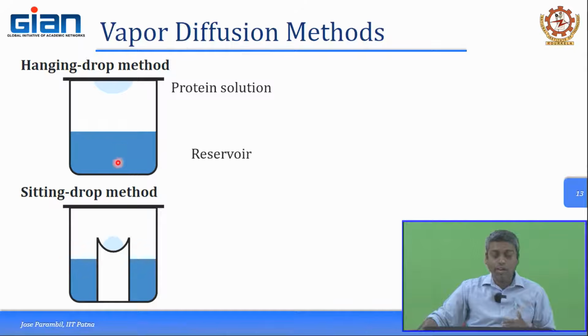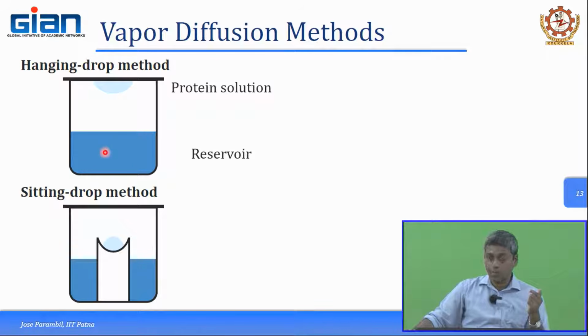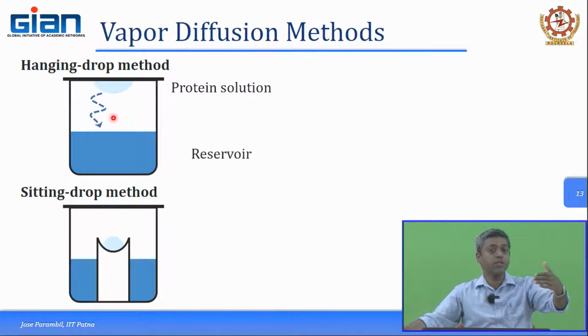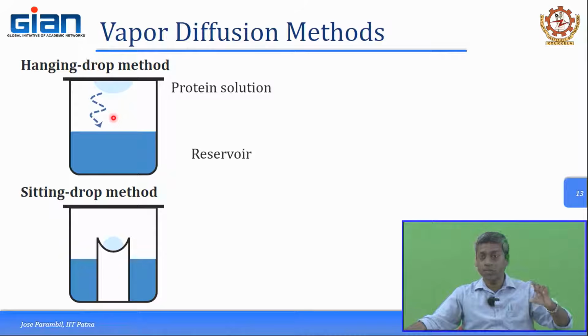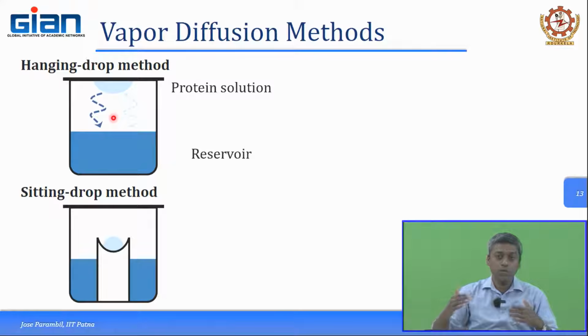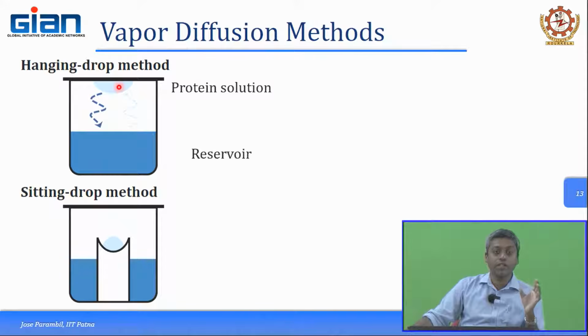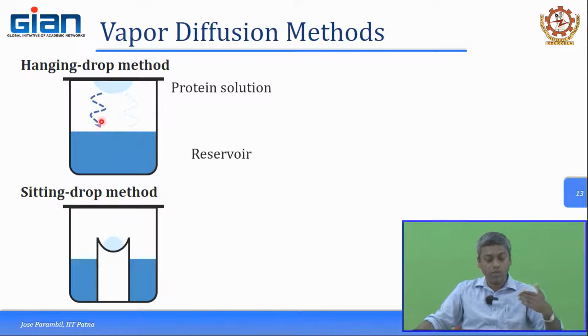Now, if you have got a higher solubility in a higher concentration of salt or buffer or maybe other polymers in the reservoir, typically the solvent used in both is the same, typically water. Water would start evaporating and moving. There would be a net movement of water from the protein solution on the top to the bottom reservoir. Simultaneously, there would also be a movement of water from the reservoir to the protein solution, but since the top solution has additional protein and the lower solution has a higher amount of buffer or salt or some other components, the net equilibrium would be driven in such a way that the water would very slowly evaporate from the top droplet and move to the reservoir.